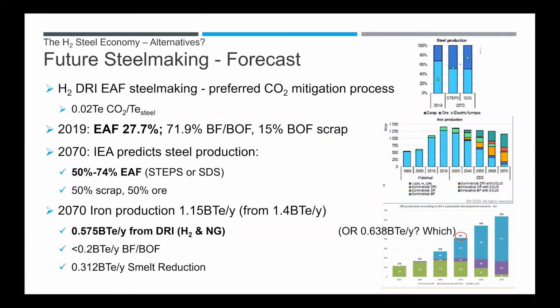We all know that it's the preferred CO2 mitigation process for the future, hopefully attaining something like 0.02 tons of CO2 per ton of steel. In 2019, we had almost 28% of the world's steel from EAFs, and we're predicting moving forward it will probably be closer to 74%. And of that, 50% will be from scrap and 50% from ore. And of the iron produced in 2070, 0.575 tons is going to be from DRI, whether it's hydrogen or natural gas based. Next, please.